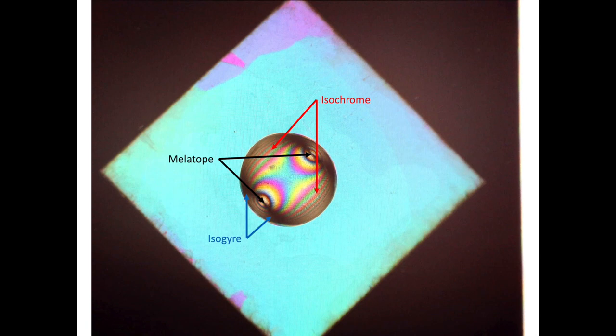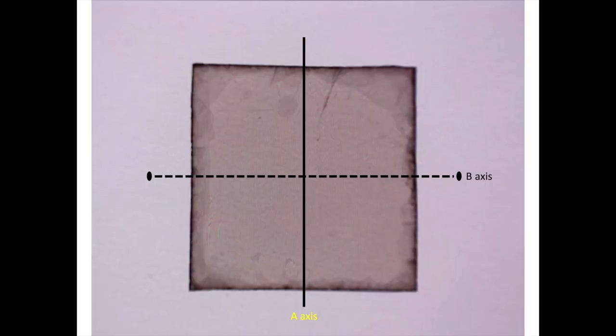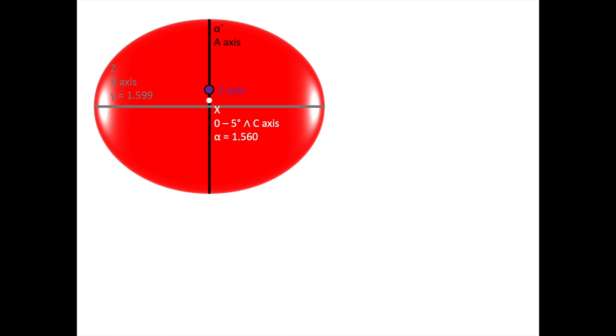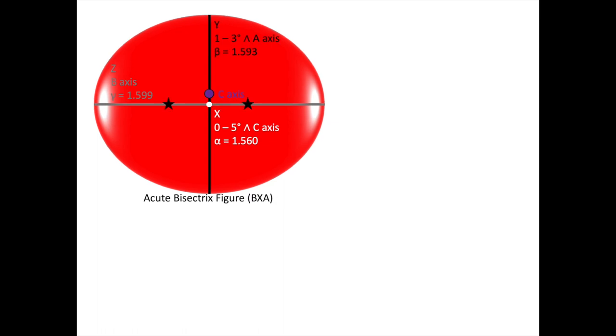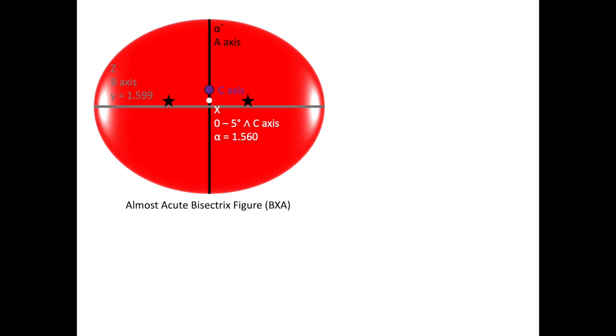In this moment, we've also now gathered enough information that we can fully understand the orientation of our muscovite sheet using a combination of crystallography and the optical properties that we're seeing right now. We know that when we're looking down onto one of these flat sheets of muscovite, we're looking onto the plane of the A and B crystallographic axes of our muscovite. And we know how the optical properties of our muscovite stack up in this viewing direction. While this view of our muscovite doesn't align perfectly with a BXA figure, it's still close enough that we can use this information in order to orient our sample.